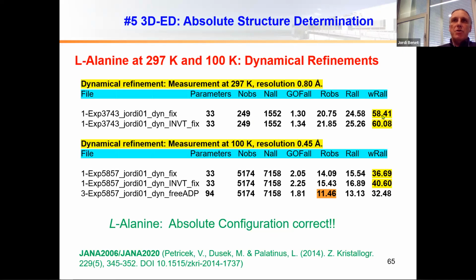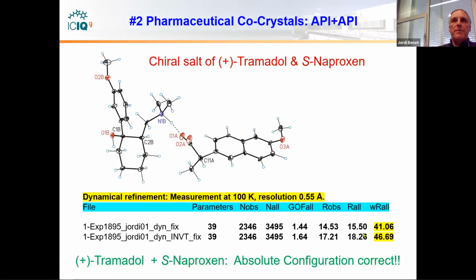So you can see that at room temperature, at low temperature, and using just the starting structure model, we could always distinguish the correct chiral form. We did this on several molecules, threonine, sugar, and we are still doing this measurement right now, so that I want to have soon a validated series of molecules measured in our system, so that I can always be quite relaxed when I get a result.